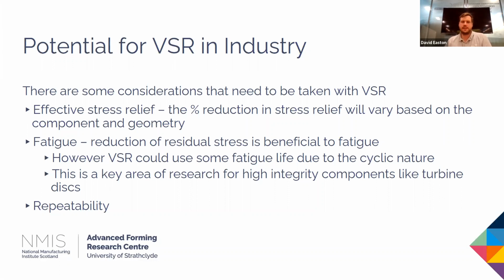Fatigue. So fatigue's an interesting one because generally if you reduce residual stresses, you're going to increase the fatigue life. Tensile residual stresses typically contribute towards lowering the fatigue life. However, there is the question of when you apply VSR, how much of that fatigue life are you using up by essentially cycling at higher loads. So for high integrity components like turbine discs or anything like that, there's significant research that would need to be done to see what effect VSR is having on fatigue. And that's an exciting area that we look forward to working on.